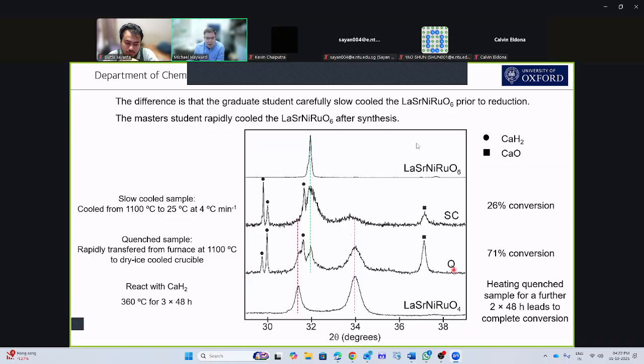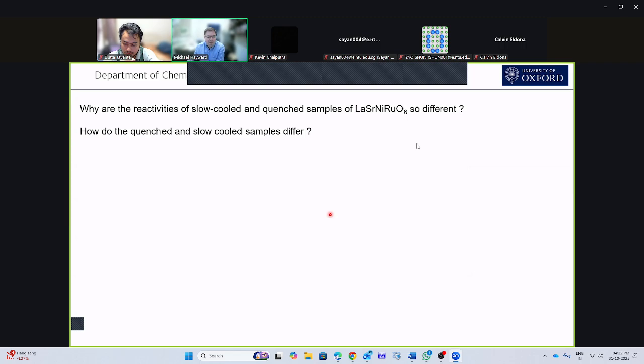And in fact, if we keep heating the quench sample for 2 more periods of 48 hours, we actually get the final reduced product. But if we keep heating the slow cooled sample, it doesn't react any further. And so a reasonable question is, well, what's going on? Why are the reactivities of the slow cooled and quenched samples different?